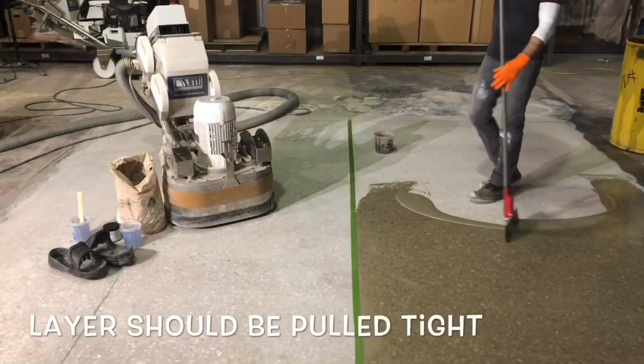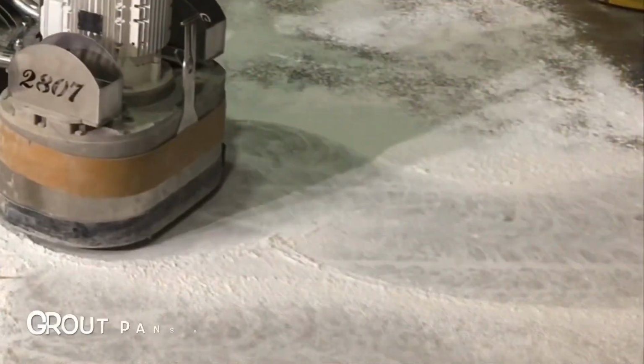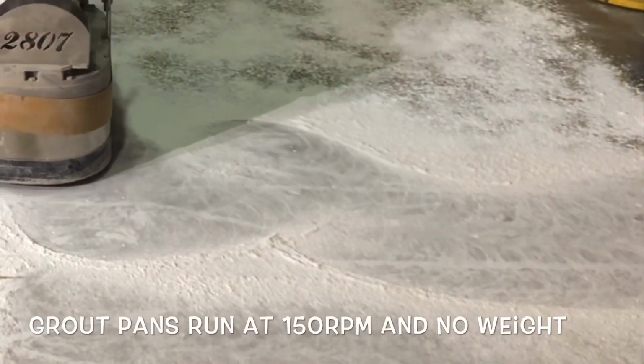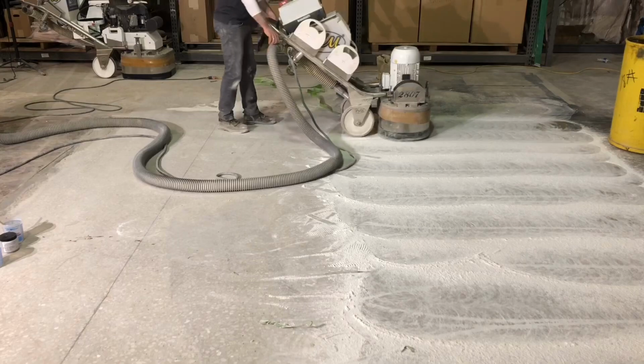Once the 70 grit step was complete and the 30 grit scratches were removed, it was decided to grout the floor. The first coat of grout was an epoxy, and the reason being is because the holes that are in the floor when it was first exposed are quite big. So we decided to use an epoxy and a marble flour process, which will help to fill the bigger holes in the floor that a urethane or epoxy coat by itself would not adequately fill.